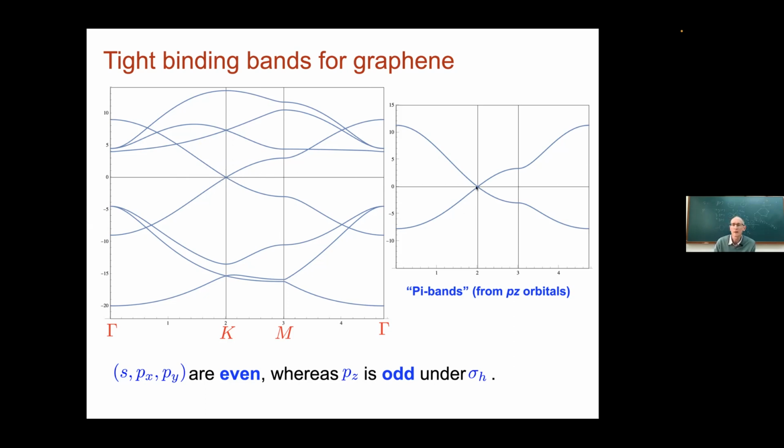This is the Dirac point, and all this ballistic behavior of electrons. An enormous amount of properties are related to the fact that this Dirac point in the band structure is right at the Fermi level. Okay, so for the rest of this lecture, we are going to consider only these two bands, knowing that they are completely decoupled from the other bands.